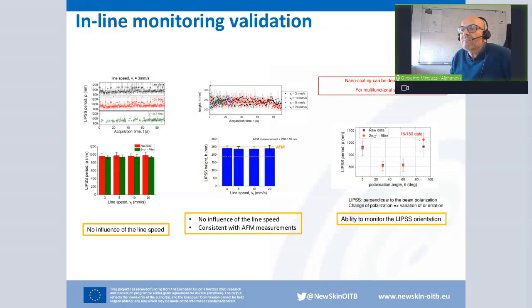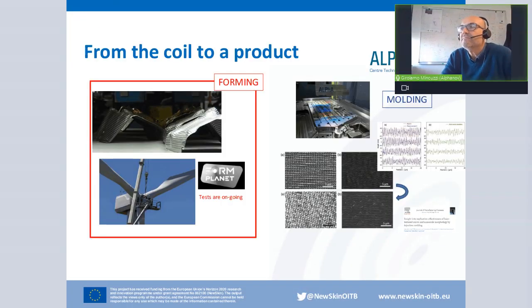In the meantime, we can measure as well the height, and the height of the structure is around 200 to 250 nanometers. The period that I previously showed is around 1 micron, a little bit less, and both are consistent with the literature. It's possible to see if the direction of the structure changes through an analysis of the polarization. Given the height of the structure, it's possible to deposit on top of our structures some nano coating to improve the behavior, to enable multifunctional surfaces.